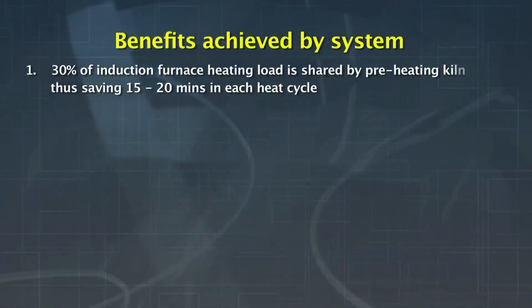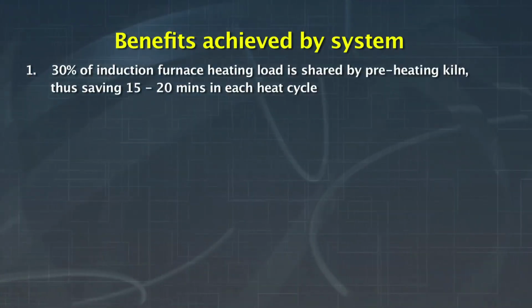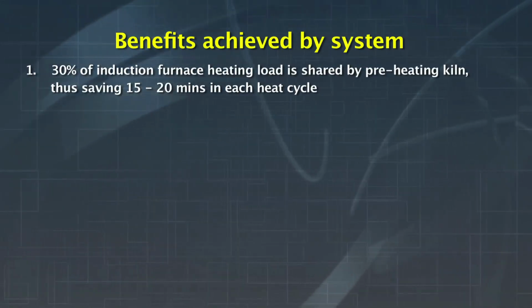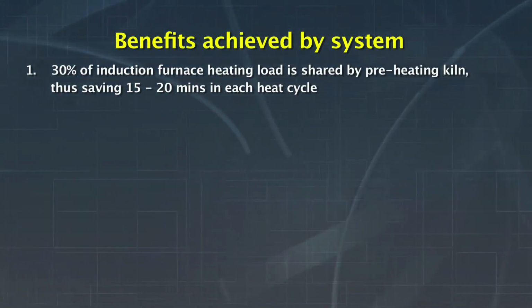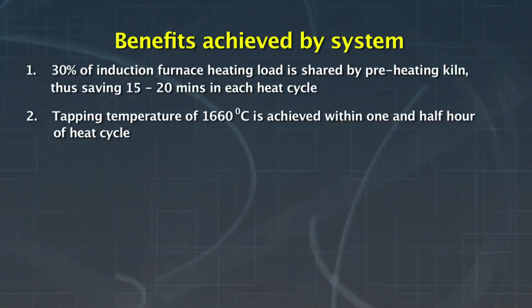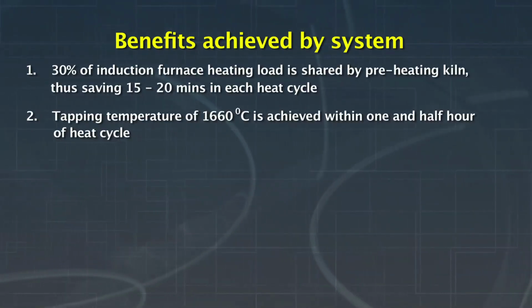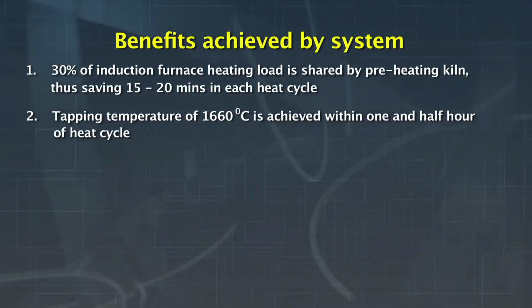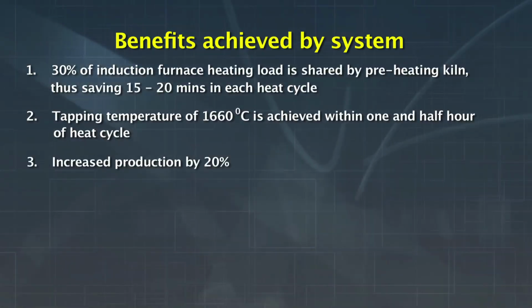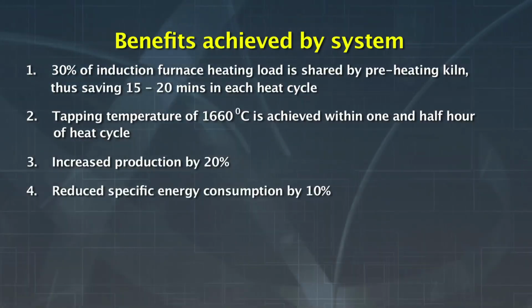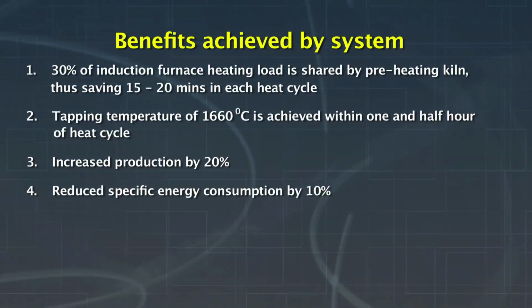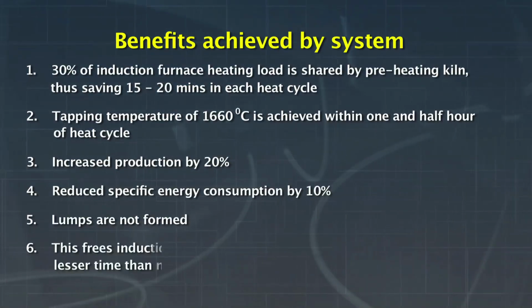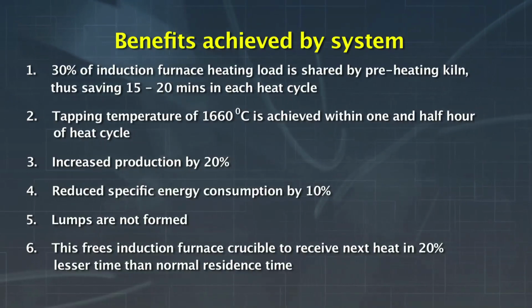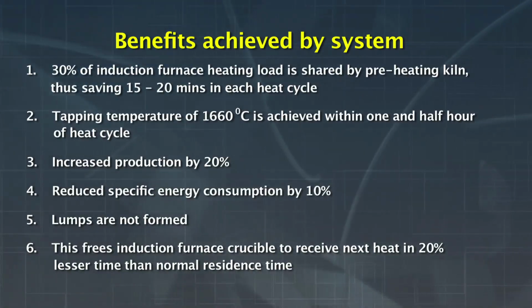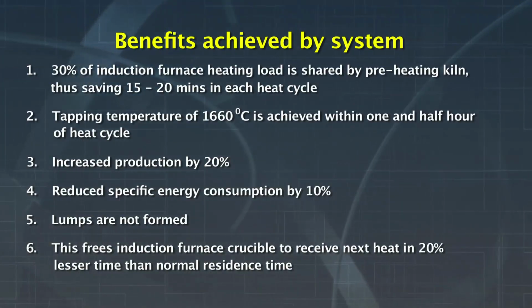Some of the benefits achieved by the system are: 30% of induction furnace heating load is shared by the preheating kiln, thus saving 15 to 20 minutes in each heat cycle. Tapping temperature of 1660 degrees Celsius is achieved within 1.5 hours of heat cycle. Production increases by 20%, specific energy consumption is reduced by 10%, and lumps are not formed. This frees the induction furnace crucible to receive the next heat in 20% lesser time than normal residence time.